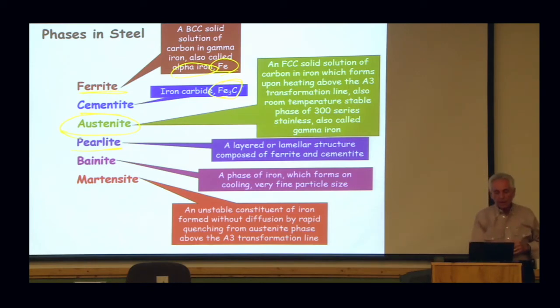The next one, if I had it in that oven and I just drug it out of the oven and let it cool outside in still air, it'll cool a little faster and then when I chop a piece of it off, polish it up, blow it up under a microscope, it kind of looks like a few limbs and some charcoal that was burnt in the grill to me. And that's called bainite. But if we yank it out of that oven while it's really hot, dump it in the water, we get martensite. And it looks like pine straw and your wife rolled the bushes. And you can tell, you may not hit it with a hammer because it'll be in more than one piece. And when it's martensite, I can't use it until I go back and put it back in the oven and warm it back up and give it some ductility.